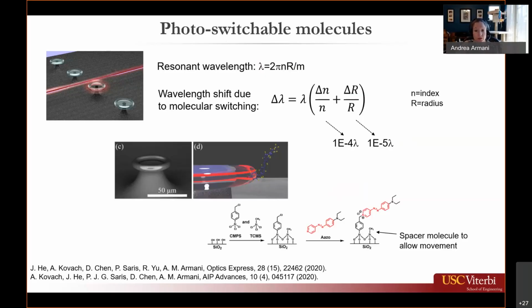The specific molecule we were looking at was an azobenzene group. This is the specific molecule. The switching or conformational change group is shown in red. When we anchored it to the surface of the cavity, it's anchored perpendicular to the surface. And when we expose it to blue light, it actually collapses or folds onto the surface of the cavity. And then when we expose it to heat, it unfolds. And it's a reversible process.